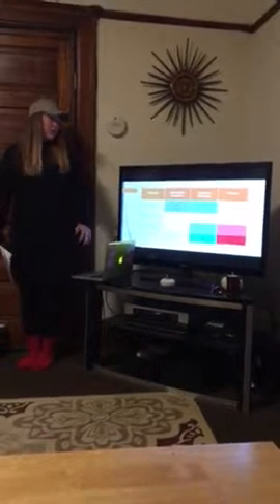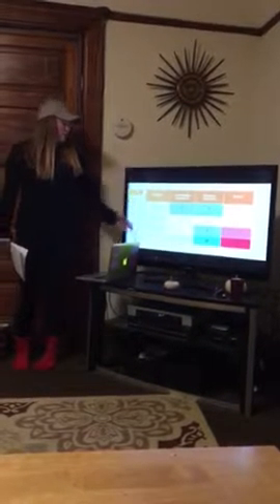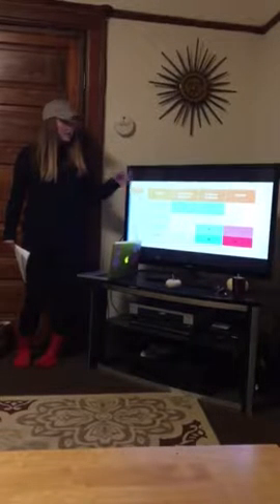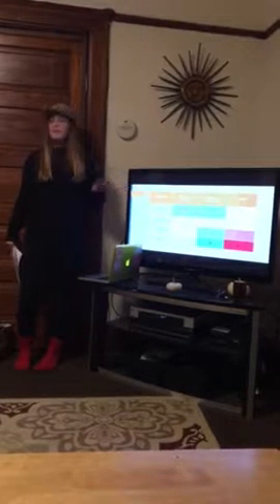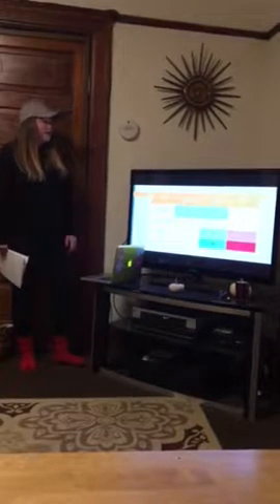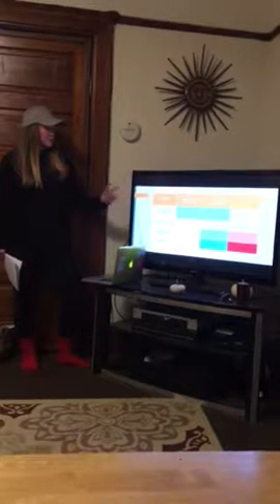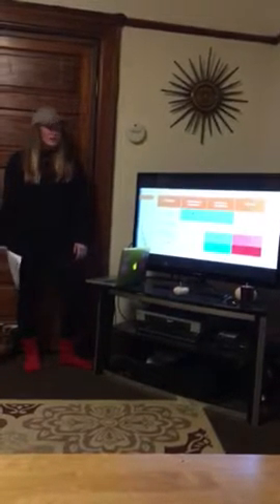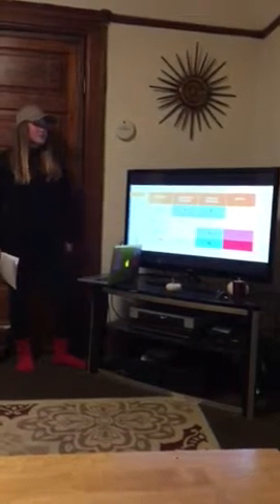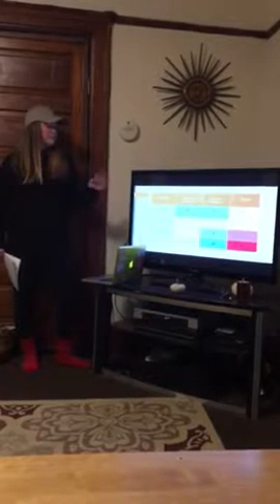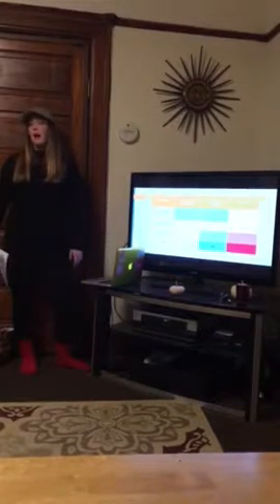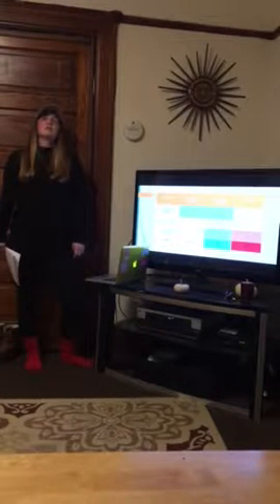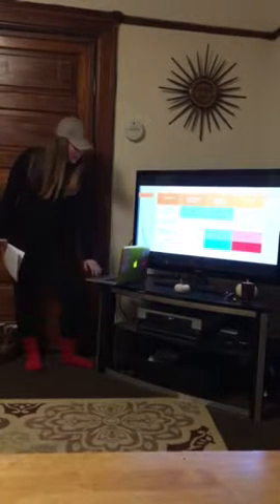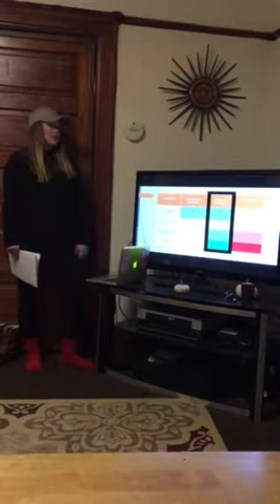In my decision matrix I created, I listed the 3 different criteria I compared and ranked each material on a scale of 1 to 5, 5 being the highest. As the graph showed, bamboo scrimber tops both the compressive and tensile strength. It also, since its inputted material value is the highest percentage, beats laminated bamboo, and both engineered bamboos beat timber in sustainability because of bamboo's high growth rate and carbon dioxide consumption and oxygen emission rate during the growth phase. Therefore, my final recommendation is bamboo scrimber.